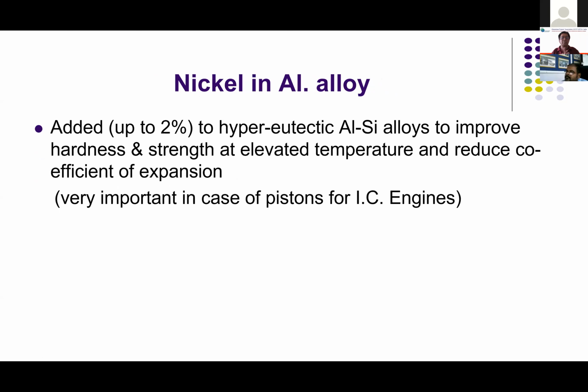Nickel added up to 2% in hypereutectic alloy, aluminum silicon alloy, to improve hardness, strength at elevated temperature. High temperature strength is achieved by adding 2% nickel. Very important in case of pistons for IC engines.